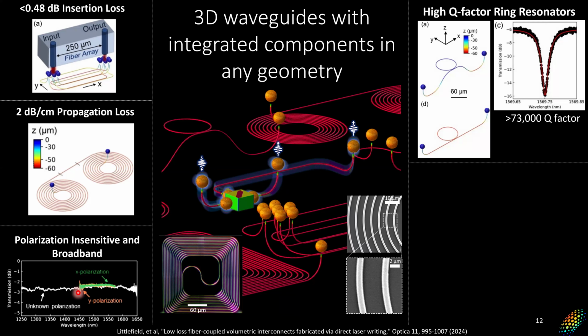And then you can build high Q factor ring resonators. This is an example of a ring resonator with greater than 73,000 Q factor. And here's where I'm going to talk about the power density, because the data we have on the maximum power density right now is from these sorts of structures, seeing how much continuous wave power you can put into these. These were tested with about 20 milliwatts continuous wave power. This Q factor corresponds roughly to about an 80x enhancement of power density. So that's about 1.6 watts confined to these waveguides that are about 1 micron in diameter, so about 1.6 watts in roughly 1 square micron.